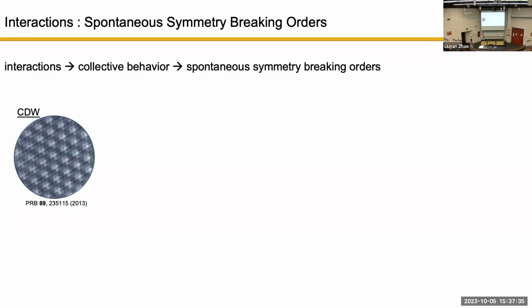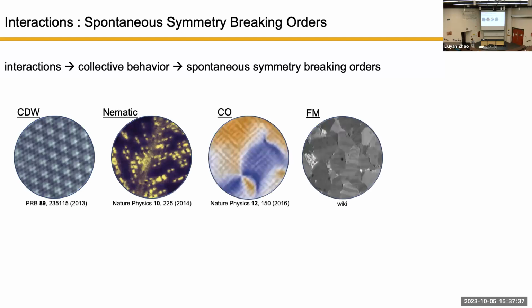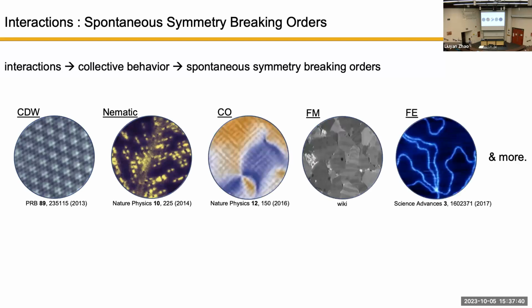We have many examples in the literature. For example, the so-called charge density wave, where you break the lattice translational symmetry, meaning that the charge part has a longer period than the lattice part. So this breaks translational symmetry. There's also the so-called nematic phase, where you start with a square lattice, and the nematic phase chooses one of the two orthogonal directions. That breaks the rotational symmetry of the square lattice. And we have charge order in cuprates that breaks both rotational symmetry and translational symmetry.